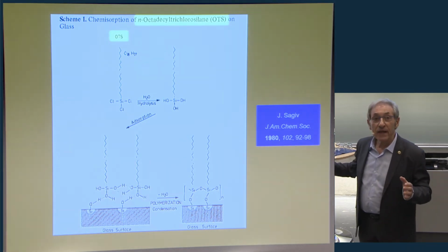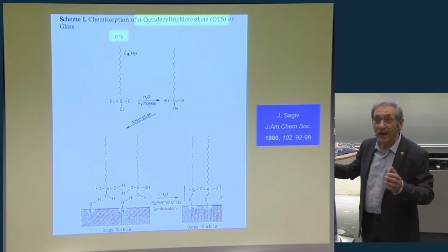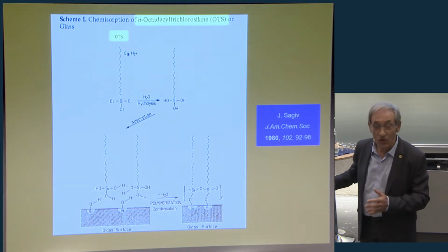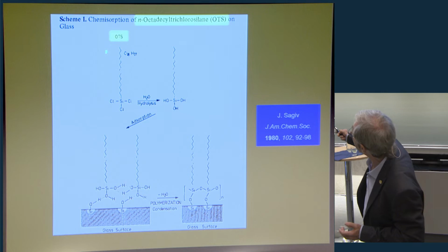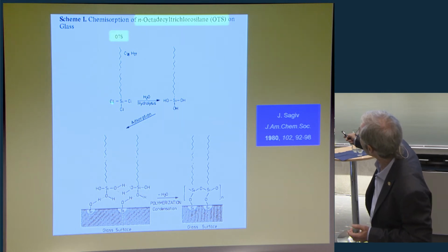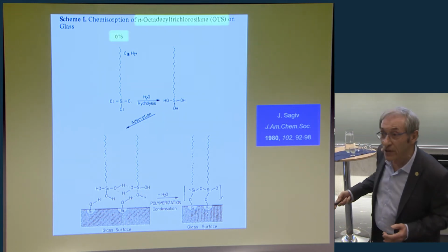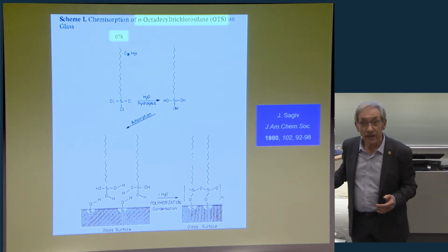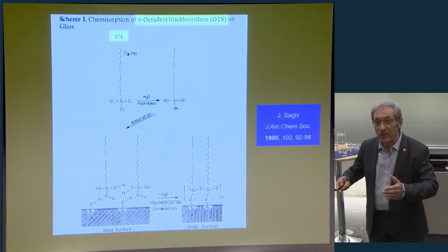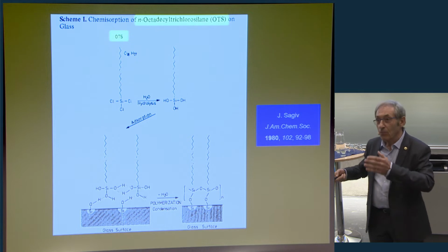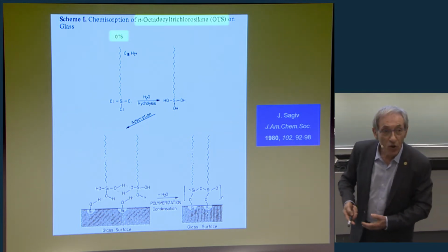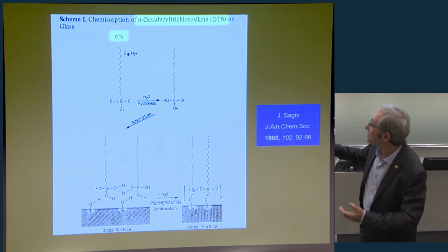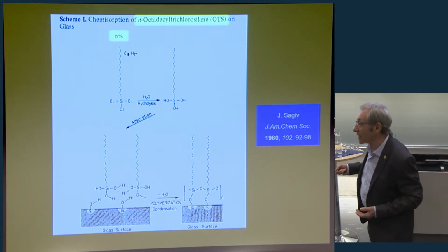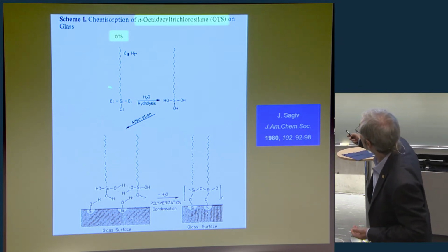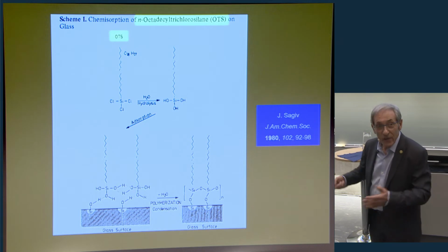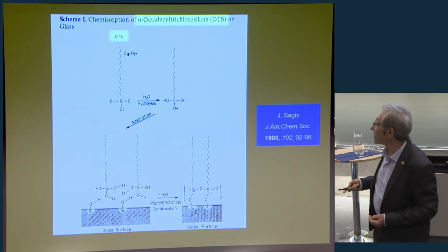process in which chemistry is combined with what we call self-assembly or adsorption on the surfaces, because the initial compound, which is a trichlorosilane, is not a polar molecule. In order to have adsorption, a surfactant must have a polar end and a non-polar end, in this case, a hydrocarbon tail. And the trichlorosilane dissolves well in organic solutions, but is not polar.